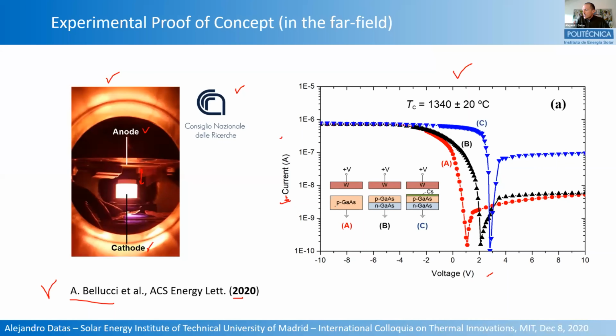This device A is simply a conventional, let's say, thermionic converter, where you have tungsten as cathode and P-type gallium arsenide anode. You have this other converter, which is already this thermionic enhanced device or photovoltaic anodes, where you have a P/N junction of gallium arsenide and again tungsten emitter, and an improved version of all of them, which is the C option, where you have the same photovoltaic anode, but this time with a cesium coating to reduce the work function of the anode.